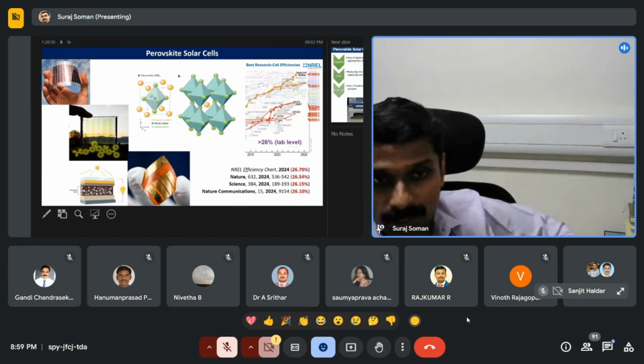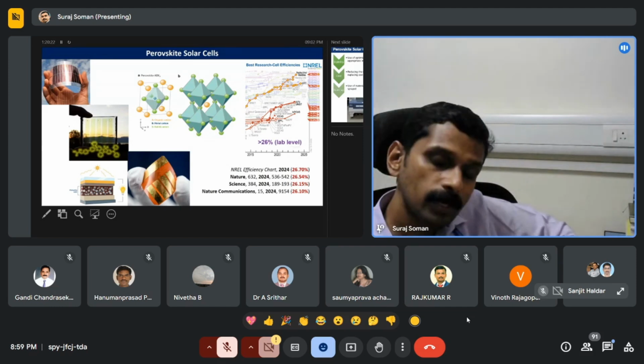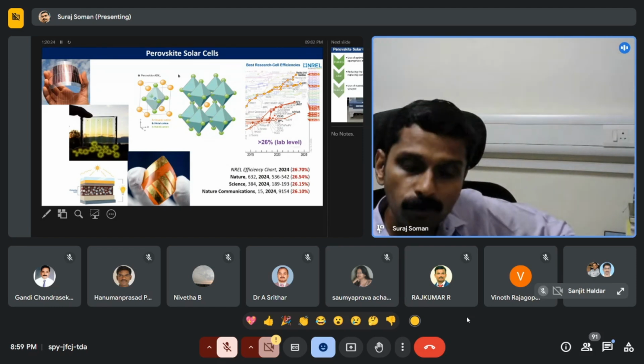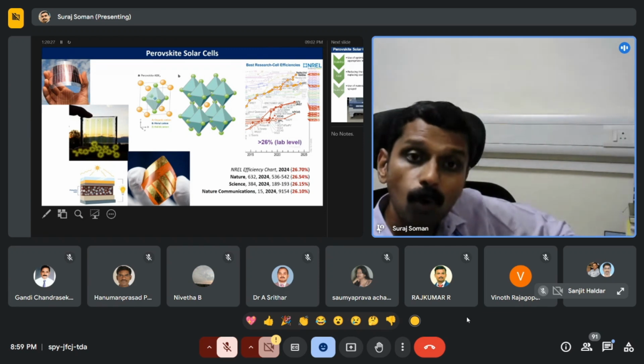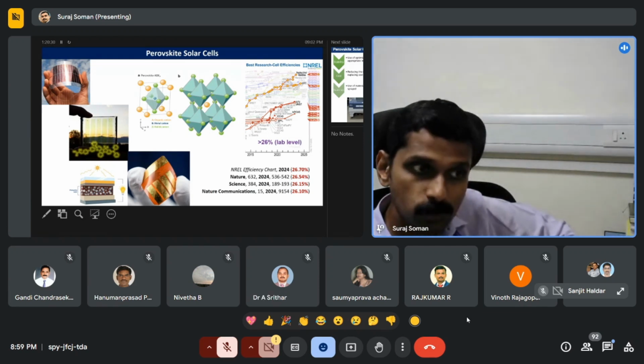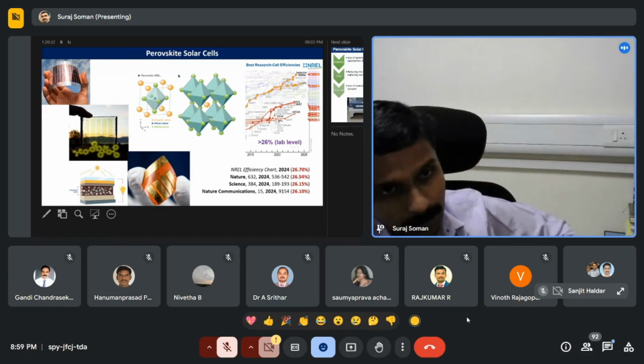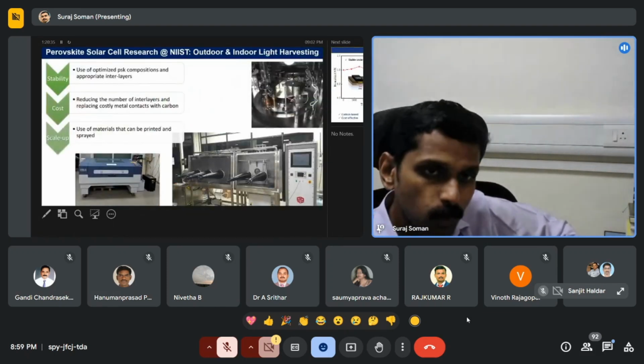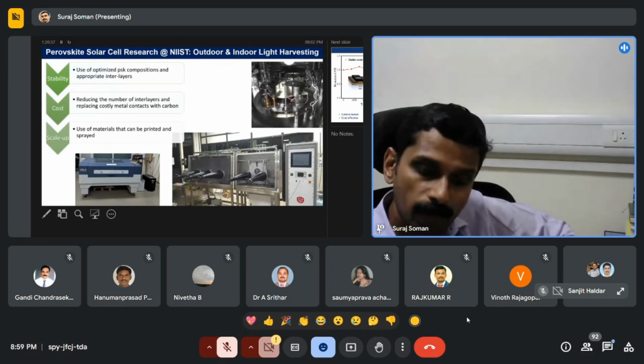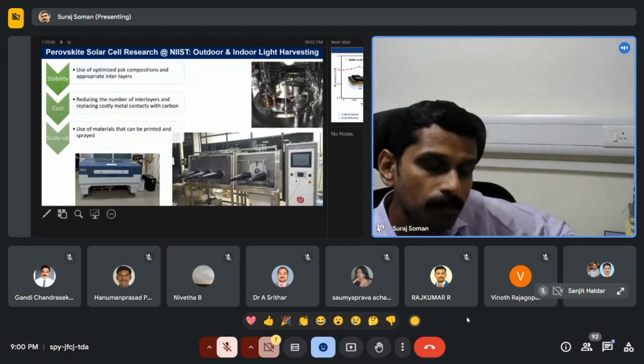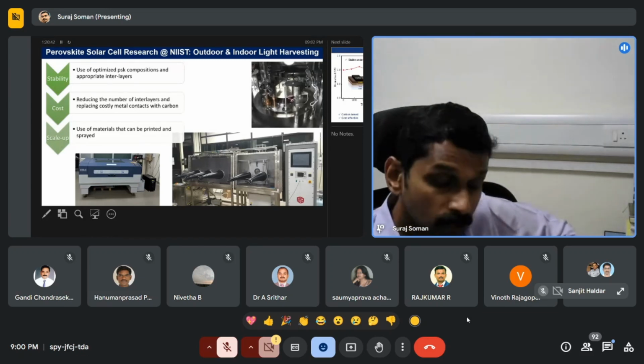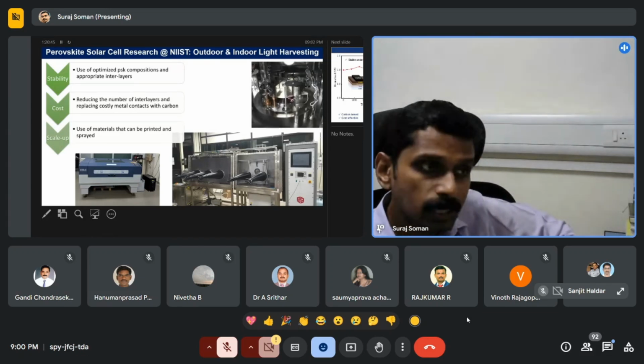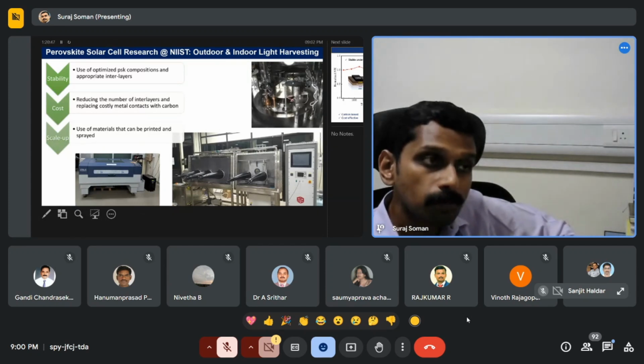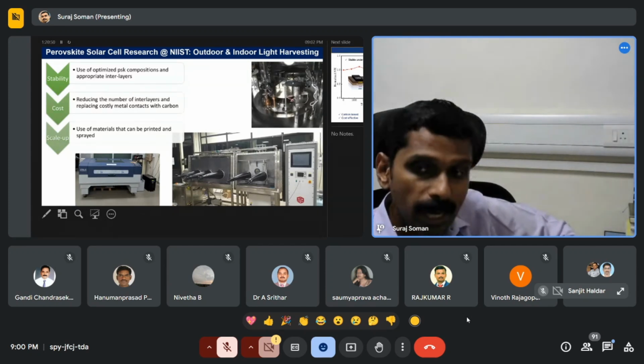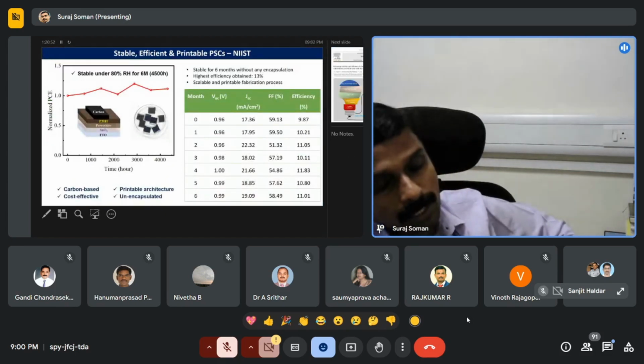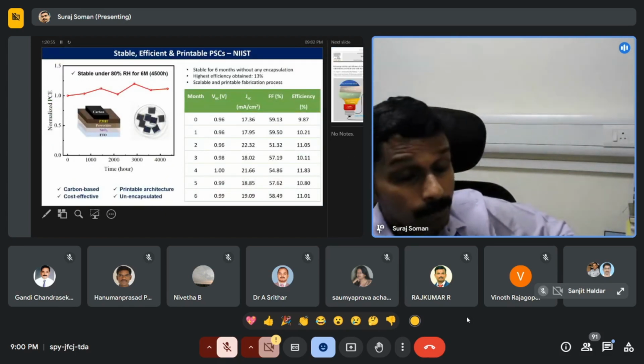The most interesting thing is that over a period of 10 to 12 years, these devices have gone from less than 1% efficiency all the way to 26% efficiency. So it's a very hot selling topic these days. We also work in this area. We have optimized a set of fabrication equipment, and a major facility has been created, and we target three major things: not only efficiency, but also stability, cost, and scale up. In this regard, we made some perovskite solar cells with a carbon-based electrode.